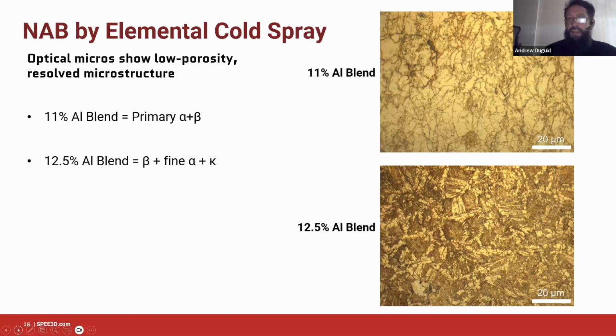The 12.5% blend obviously is mostly decomposed beta phase, sort of beta prime or decomposed beta once you've aged it. There's obviously a little bit of fine alpha phase, and then you can't actually see it there, but there's actually quite a lot of fairly coarse kappa phase distributed throughout that microstructure. It's not very clear there, and we go, okay, we don't like seeing an awful lot of intermetallic in a microstructure, so that might tend to push us back towards the 11% blend. So if we'd like to move on to the next slide.